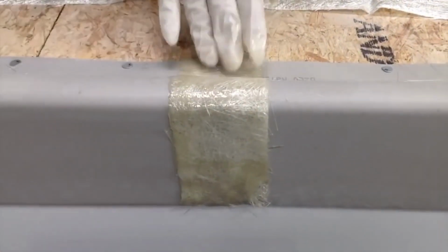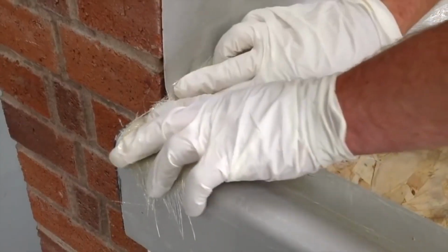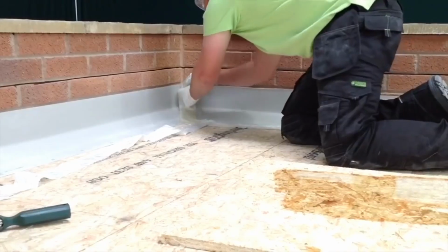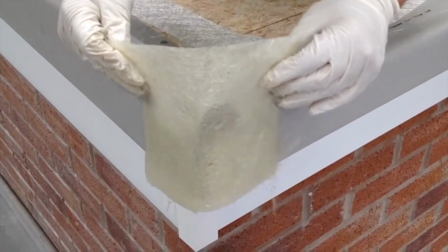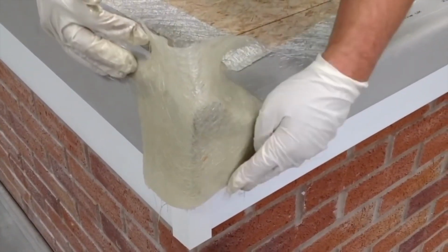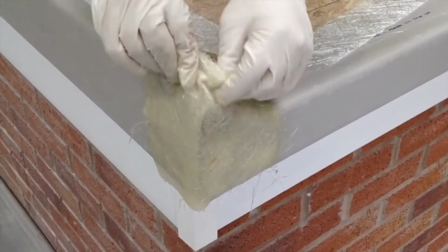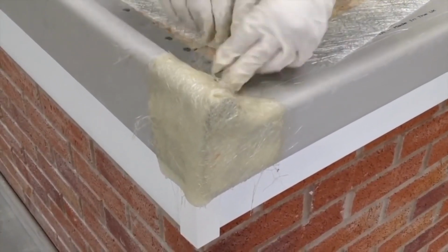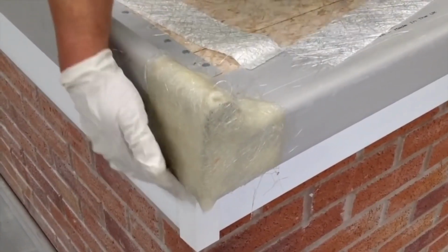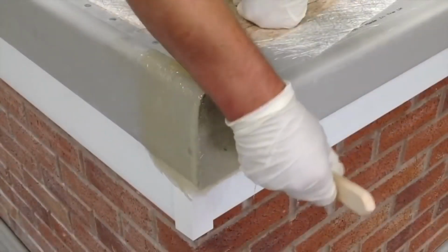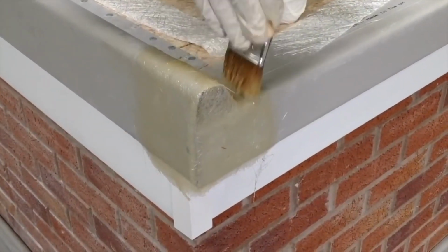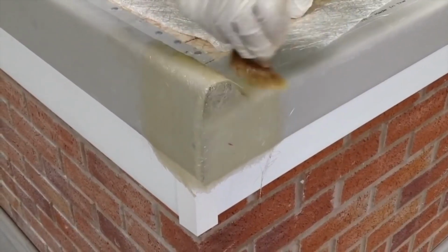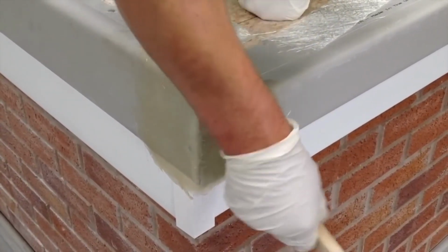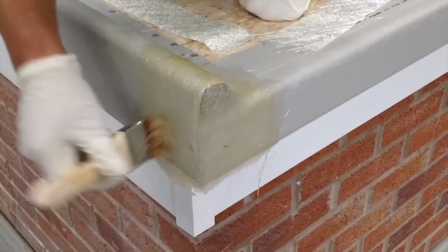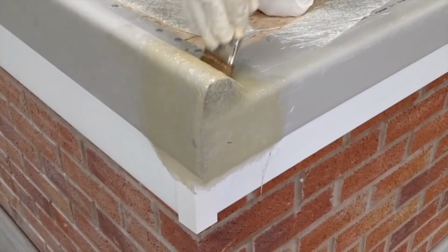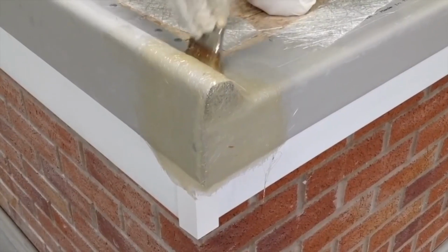Lay the bandage strips over any joins in the trim and in areas where two trims join together. Take the square piece of bandage and lay over the end of the A200 and B260, ensuring the whole void including corner is covered. After a minute, the resin will saturate the mat and it can be molded to shape. Using a brush with a little resin, dab away from the corner, pulling the bandage tight and down to the bottom edge of the drip trim, making sure the bandage is saturated with resin and doesn't contain any trapped air.